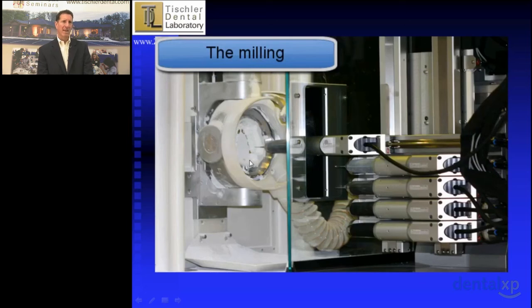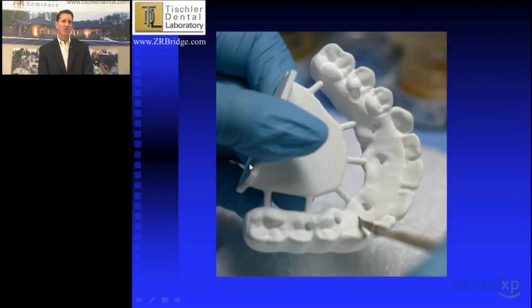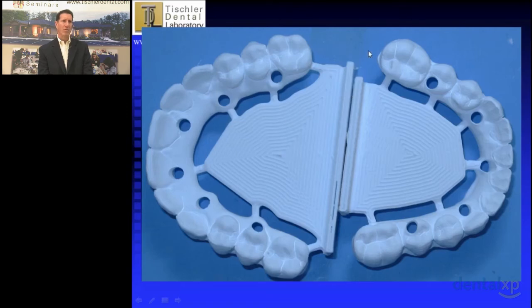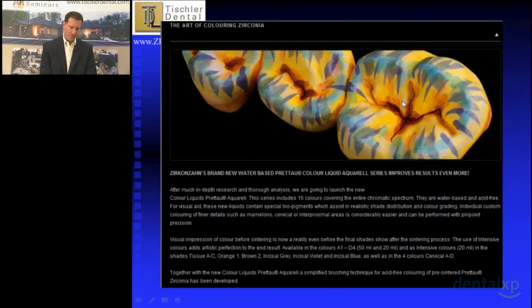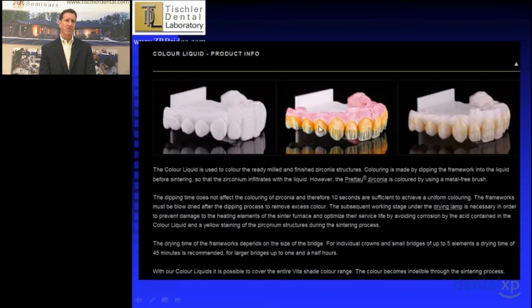Now, I mentioned earlier that the pre-sintered zirconia is 20 to 25% larger than the final product. So my lab now will take this initially milled zirconia, and here is a maxillary mandibular arch, and we will now apply stains to this. So we can now intrinsically stain this prior to the final sintering. So here's what the stains look like, and we now put this in the sintering oven, and this sinters for about 10 to 12 hours at about 1500 degrees Celsius and shrinks between 20 and 25%. The Prettau zirconia, I believe, shrinks 22% exactly.